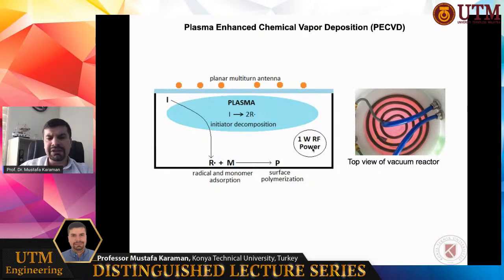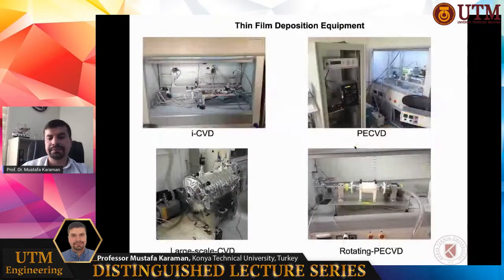I want to explain this. Very high polymer deposition can be obtained at power levels as low as 1 watt, which is very, very low power level. As I said before, it is very important to have polymers deposited at low plasma powers to prevent the monomer dissociation and to help to have polymers with very high functionality.